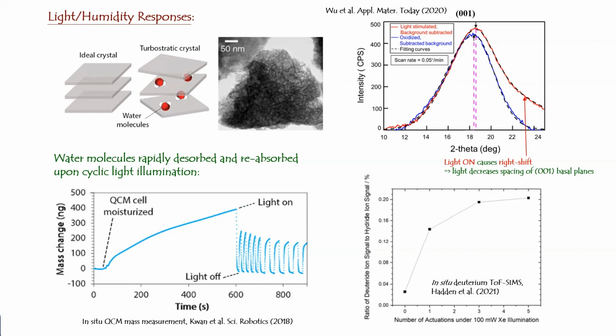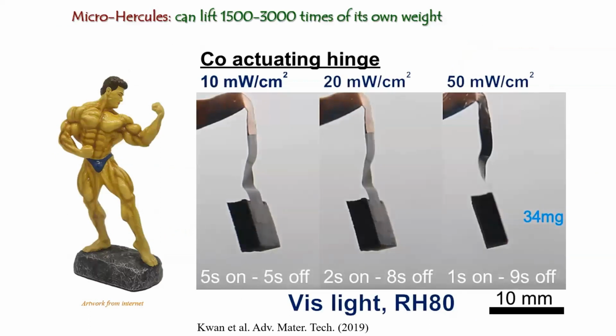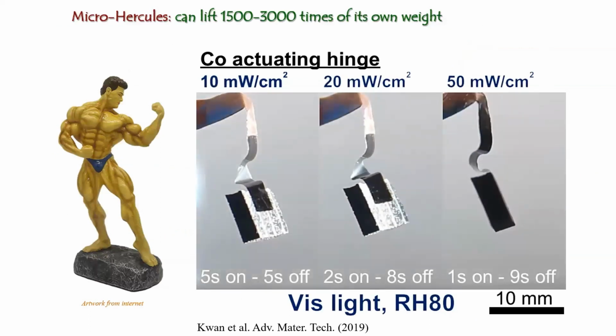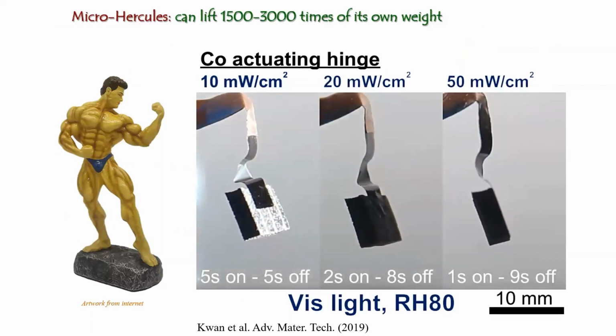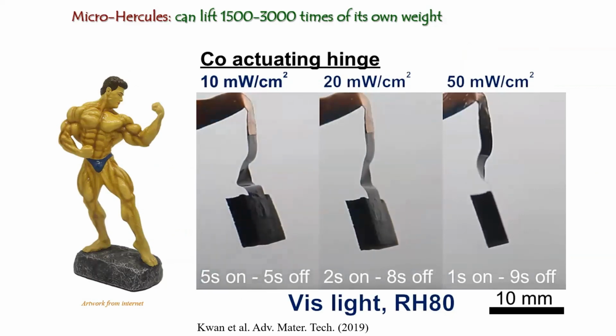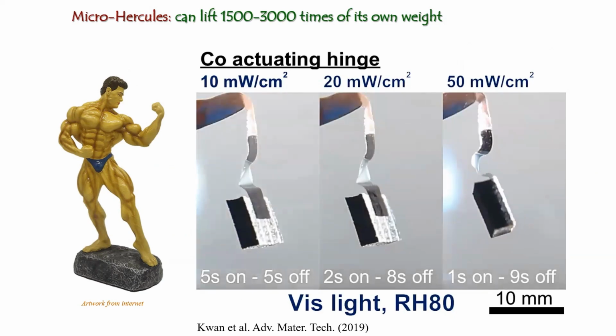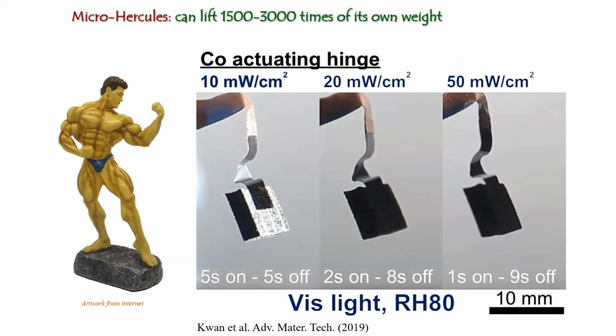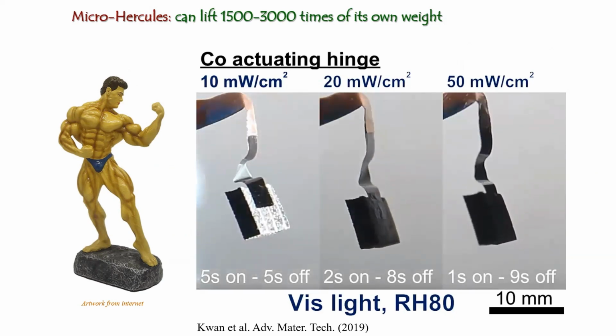So by running the sample through this time-of-flight SIMS, they can actually prove that it's the water going in and out of the material when you have the actuation going on. So in terms of the load carrying capability, it is quite a big leverage. The material can lift a few thousand times its own weight. This is the cobalt system, the COH system.